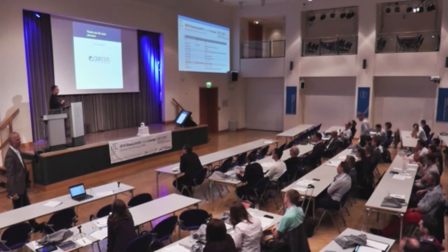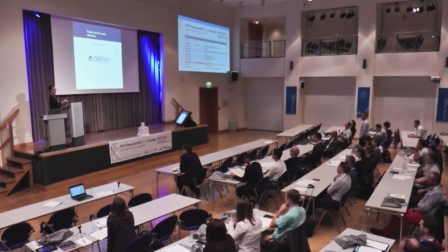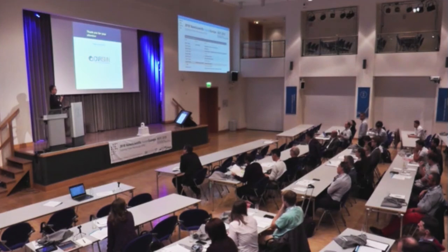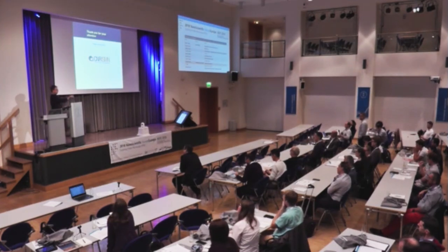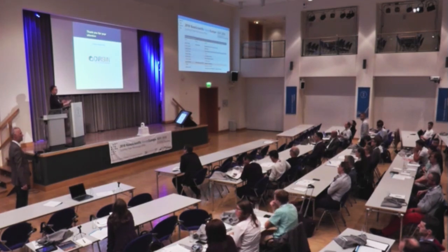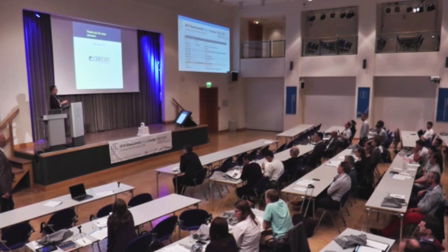I need another technique to investigate how the doping is diffused inside, because essentially the change of the surface energy, or the property of the surfaces, if you want the number of hydroxyl groups, has been changed by the diffusion of the doping from the silicon to the silicon oxide when the native silicon oxide is formed. For example, I have done a simple experiment. You put your silicon substrate in HF. You fully remove the silicon oxide, even the non-stoichiometric one. You have a flat silicon surface, and then you wait roughly 1 month to have exactly the same silicon oxide. And the properties come back exactly to the original ones.